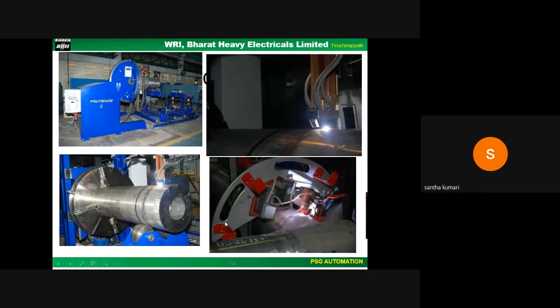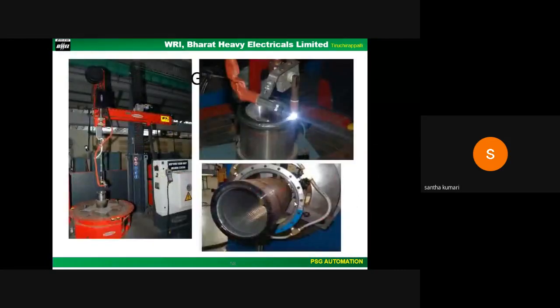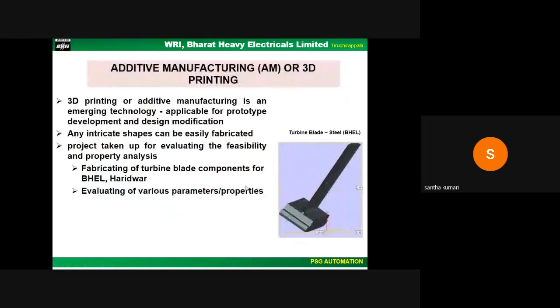Hence, by viewing the weld pool and the filler material melting through the camera, we will be able to align the torch to the groove. This is another robotic system available for cladding of valve components. You can see here valve components for internal or external cladding. And there is an automated pipe cutting also available now in our shops, including chamfering along with the pipe edge preparation. So we also tried the feasibility of trial 3D printing for turbine blade components.